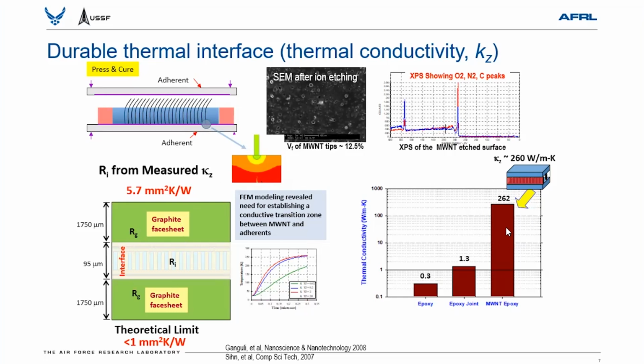And we measured thermal conductivity through thickness over 260 watts per meter Kelvin, as compared to without such nanometer engineering, which is near 1 or 2 watts per meter Kelvin. So if you do the right interface, that's the key towards improving properties with the nanomaterials. Then indeed you can achieve the property that is missing without doing proper engineering.